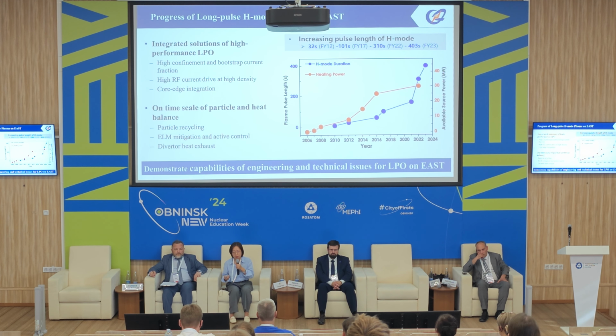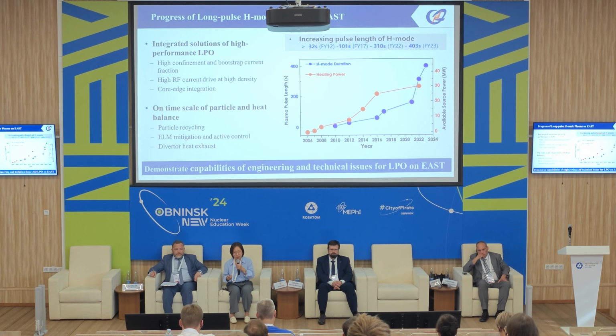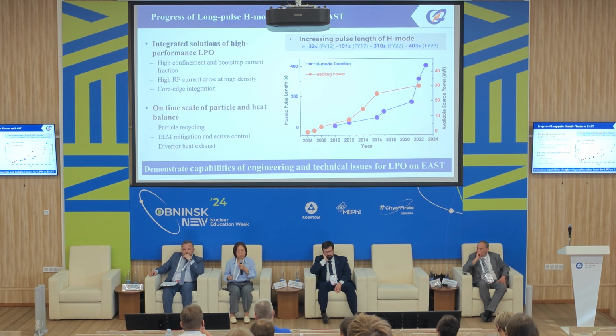For this long-pulse operation, an integrated solution of high performance has been explored to achieve high confinement and bootstrap current fraction, to achieve high RF current drive at very high density, and to achieve a good core and edge integration. Also for the long-pulse operation, the particle and heat balance should be controlled very well. For example, the particle recycling, how to control the ELMs and mitigate the impact on the first wall, and the divertor heat exhaust should be controlled very well. So now, after many years of experience, I would say all of these results demonstrate our capability to handle the engineering and technical issues for long-pulse operation on EAST.